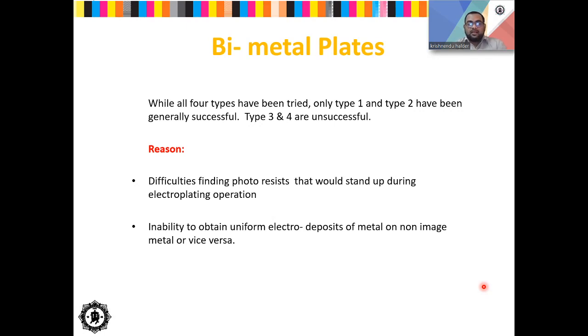And it's very difficult to create a uniform electroplating layer of your image or non-image metal with the presence of your hardened coating. So to create this uniform thickness of your image or non-image metal which is being electroplated over the base metal, it's very difficult. It means the inability to obtain uniform electrodeposits of metal on non-image metal or vice versa. So it's very difficult to control. So the plate maker can't have any control over this particular electroplating process.